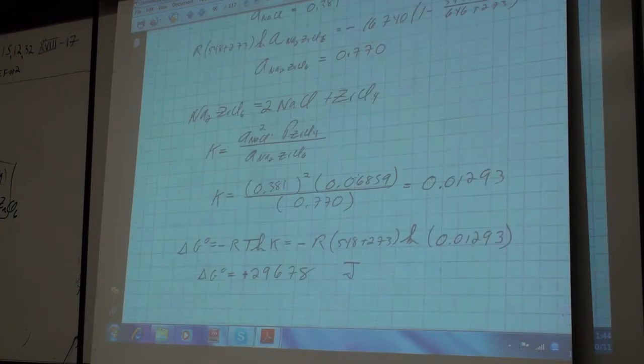That gives us the equilibrium constant, because we have the two activities of a solution which is in equilibrium with the gas phase. So these have to be the activities at the same point. You could measure them at other compositions, and you should get the same equilibrium constant, but this is easy to measure because the eutectic composition is the temperature where the two liquidus lines converge, and so you get the activities of both. That's the only point of the diagram in which the phase diagram gives you the activities of both components simultaneously.